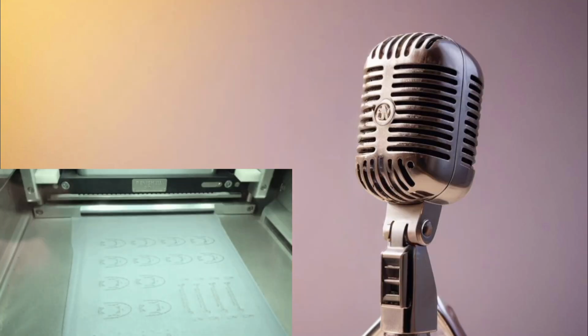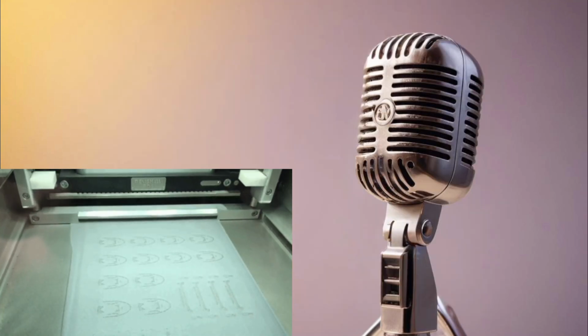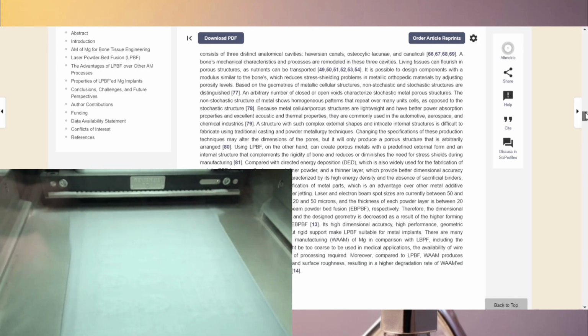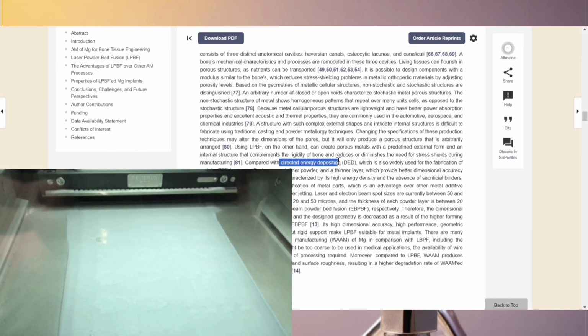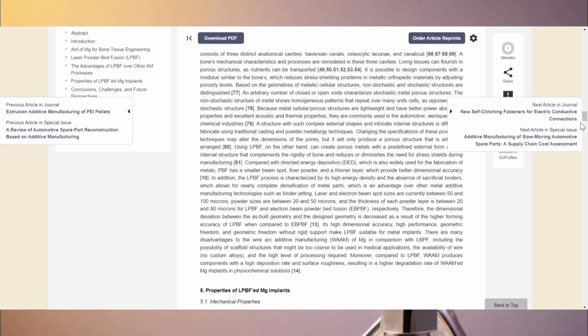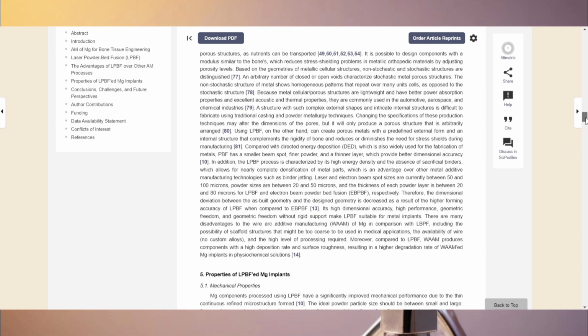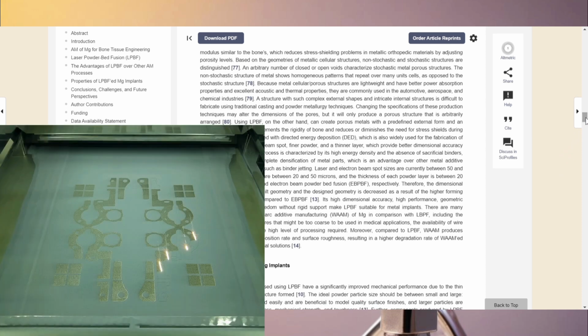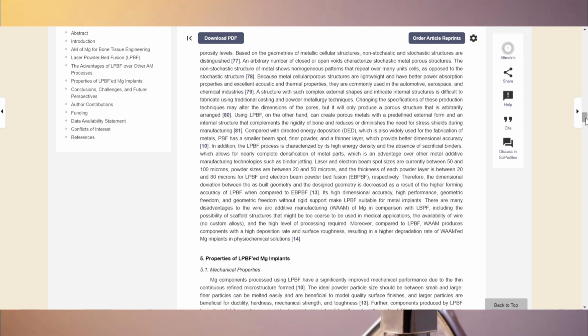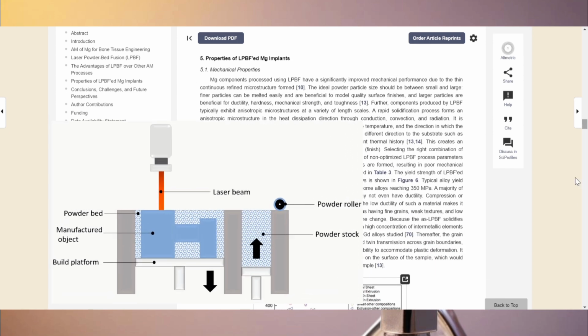It can fabricate porous metals with a carefully designed outer geometry and an internal structure fine-tuned to match the rigidity of bone, reducing the stress shielding often seen in manufacturing. You might wonder why not just use directed energy deposition, another form of additive manufacturing. The key difference is that LPBF typically uses a smaller beam spot, finer powders, and thinner layers, leading to higher dimensional accuracy and more precise details. It also works with higher energy densities, melting metal powders without needing sacrificial binders.